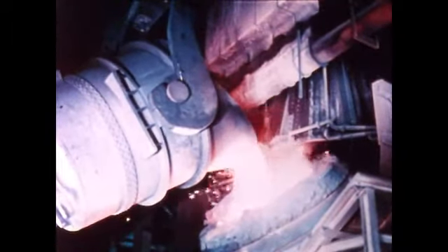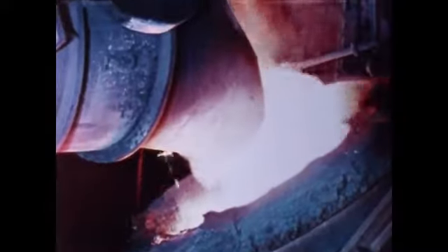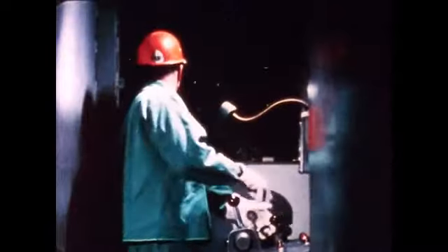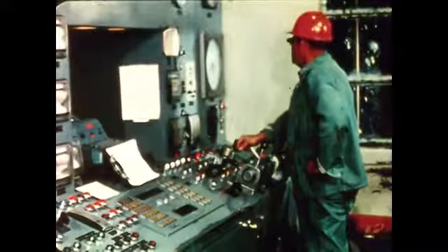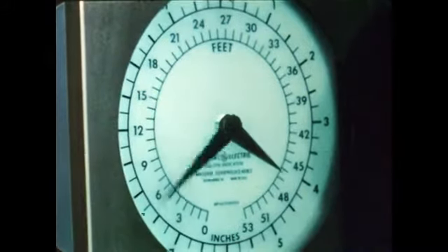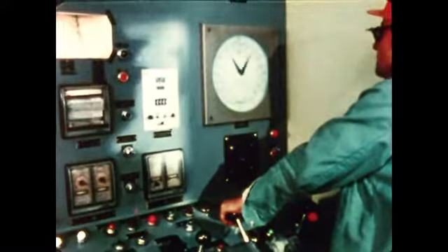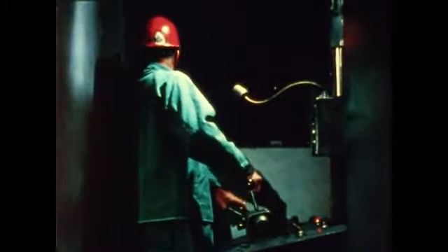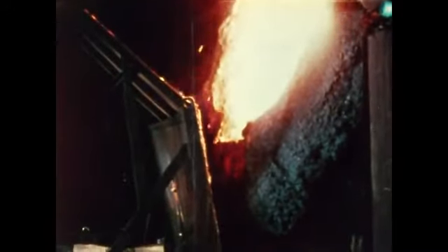It begins its life in the heart of our modern basic oxygen furnace. The furnace is first charged with molten iron from the blast furnace. Then, from the oxygen lance that probes deep into the fiery liquid, oxygen is injected at a speed faster than sound. Inducing oxygen in this manner speeds the oxidation process, saving time and allowing for accurate control of the properties of the liquid steel as it evolves out of the molten iron.